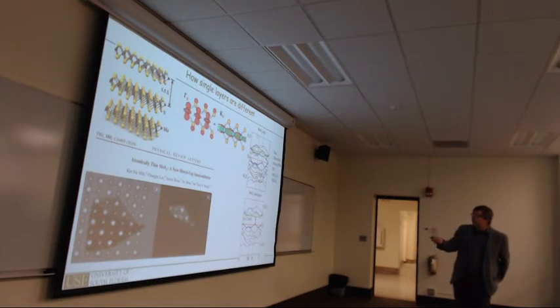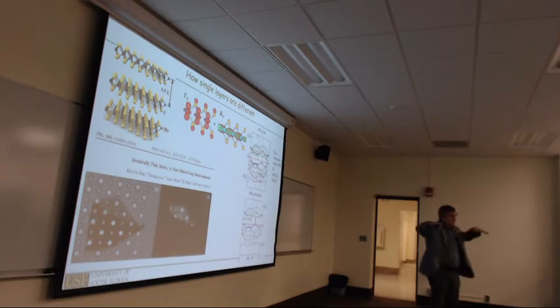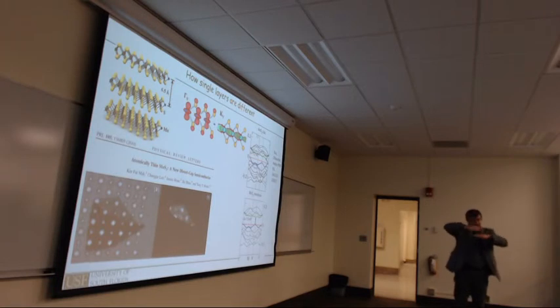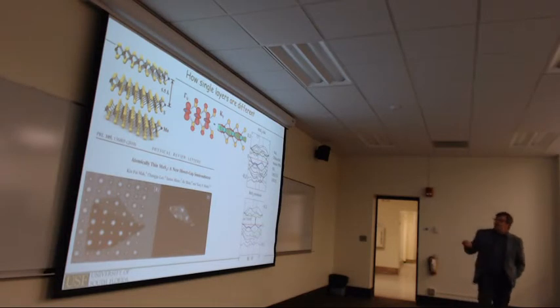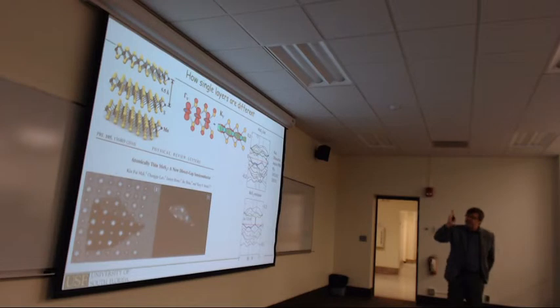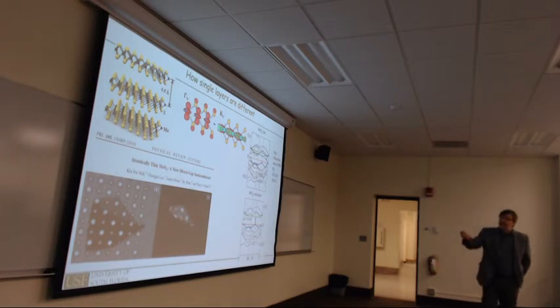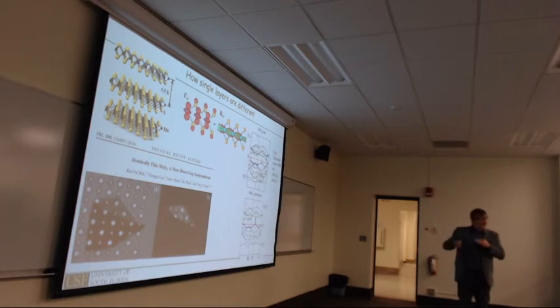So if you see here, it's a K point. Here, essentially all the molecular orbitals are located at the molybdenum plane and are in the plane of the molybdenum plane. So if you stack those on top of each other, these molecular orbitals don't see anything of the molecular orbitals of the next layer, and those orbitals do not interact at all. While at the gamma point, which is up here, you have these orbitals, the molybdenum d_z2 orbitals that stick out of the plane. And so if you have another plane on top, then these orbitals can interact with each other and partially overlap, which gives a rise to their binding energy being higher, and that makes the gamma point the valence band maximum because of the overlap of orbitals.